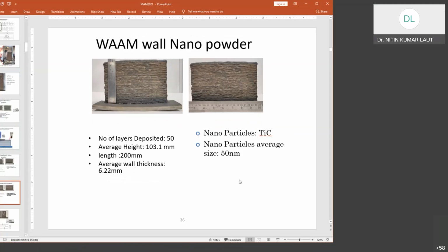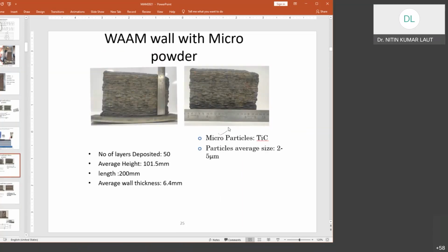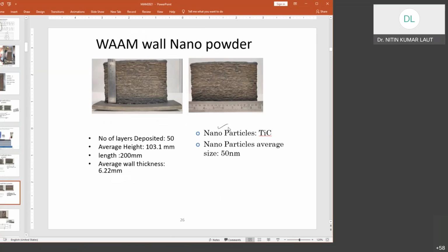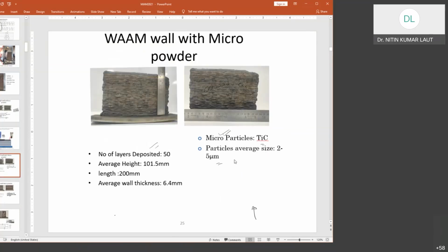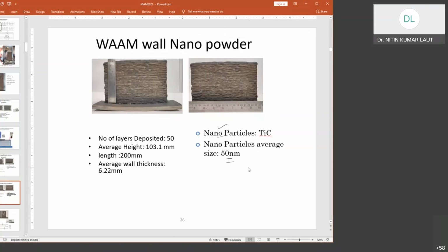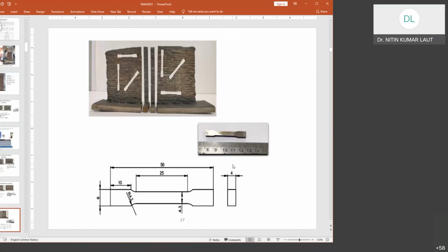Yeah, this is again some more confirmation with nano powder. The earlier case was micro particles, and the other case is nanoparticles of 50 nanometer size, whereas in the microparticles it was 2 to 5 micron. So see, we were having three variations. One was without powder, but with powder also we have developed the product with micro and nanoparticles.